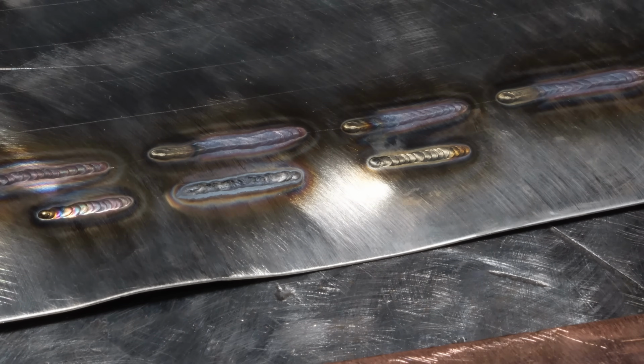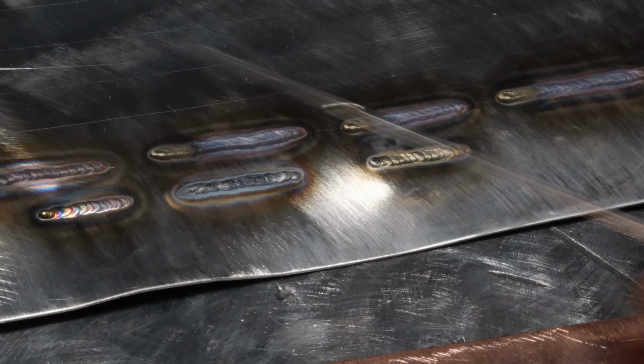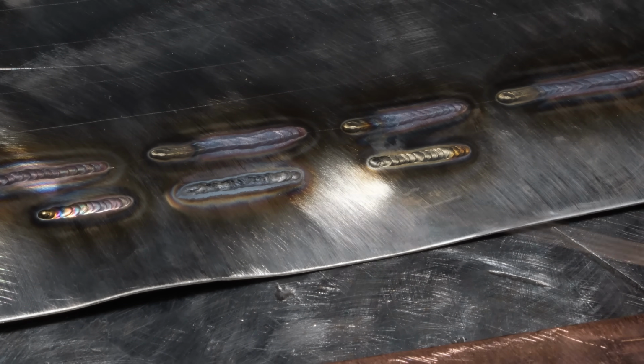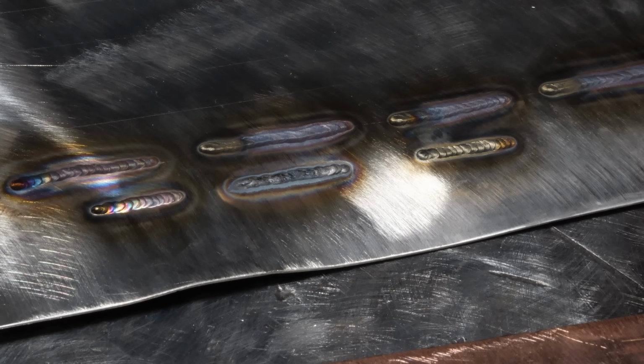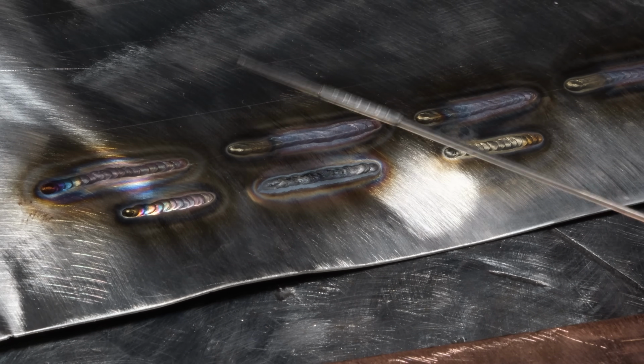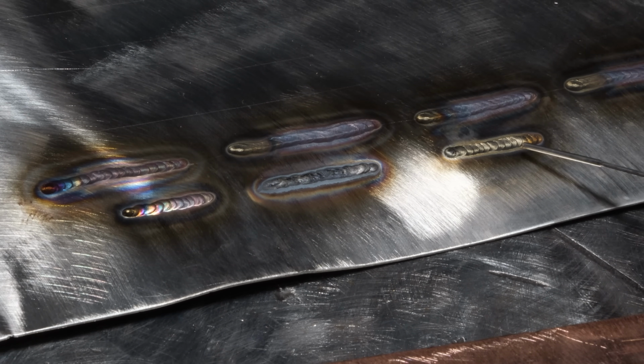Now, the interesting thing with all of these is, for the most part, like this, not so much this, but this, they're all acceptable welds, and you're going to have a very hard time on thin wall stainless getting pure silver welds without a ton of argon coverage. In most cases, it simply isn't necessary to achieve that, but now you know how critical argon coverage is for getting results. Now let's take a look at the back.